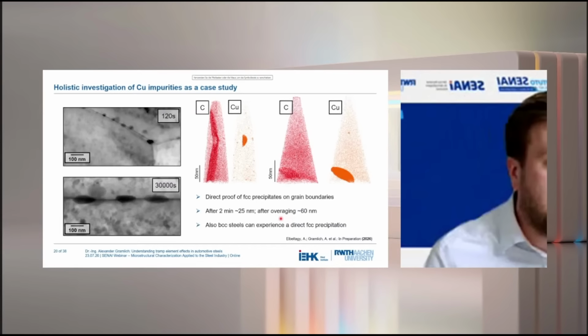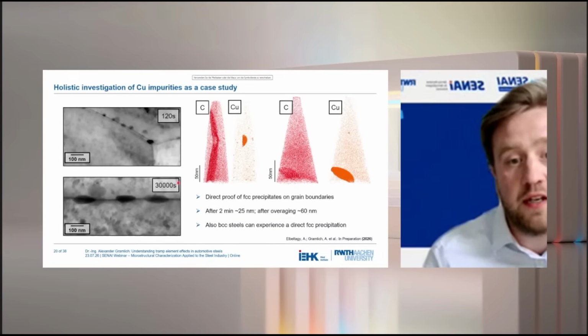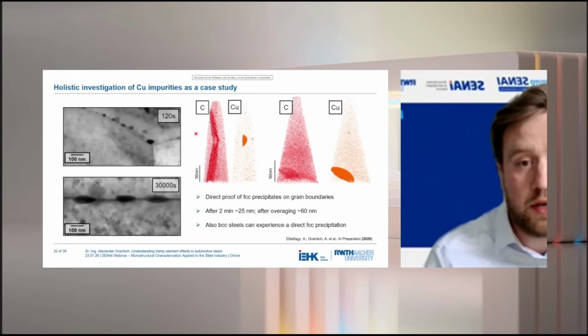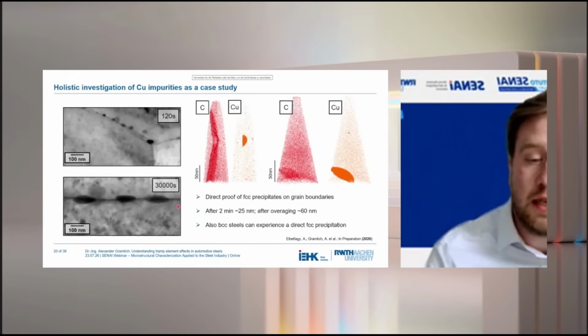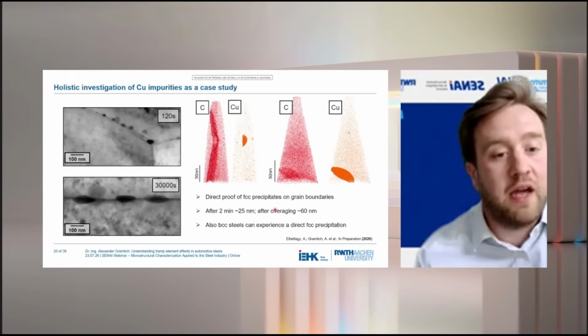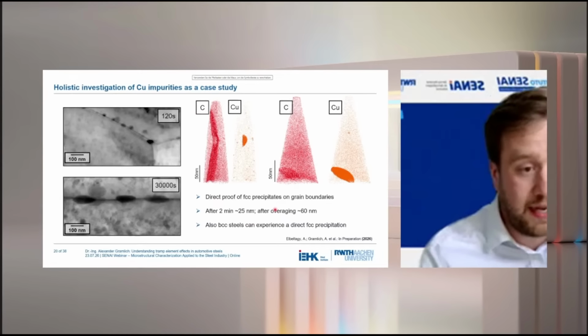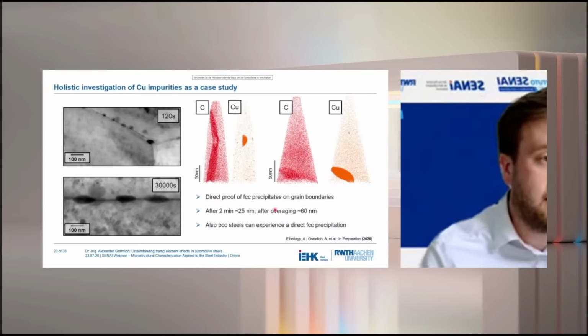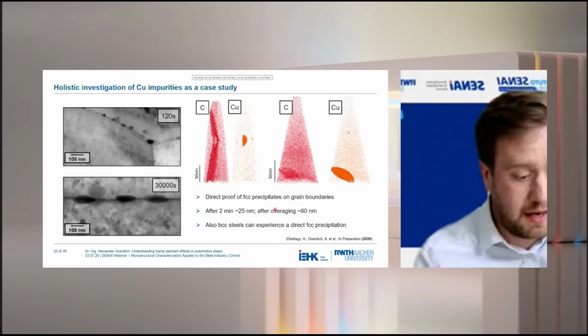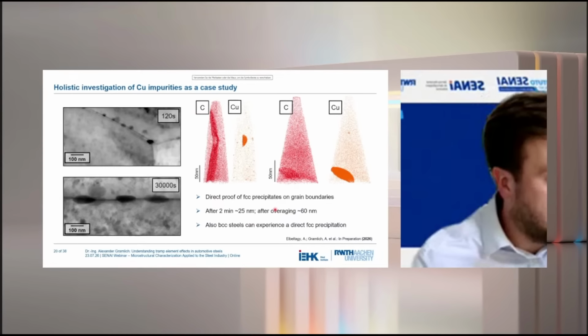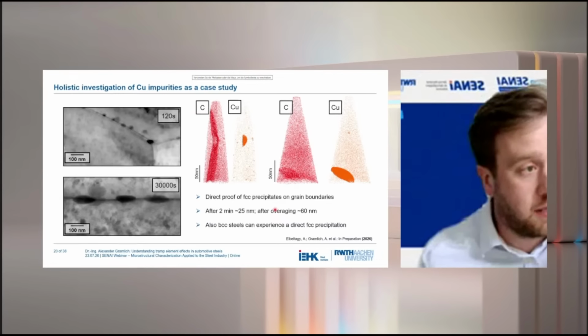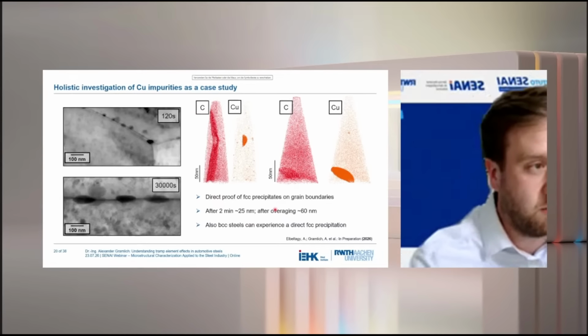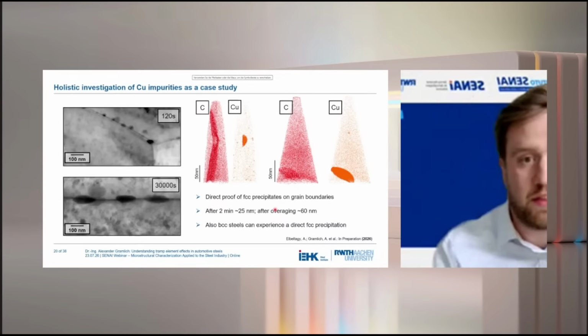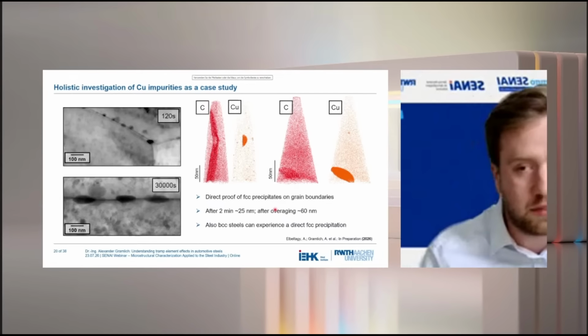Finally, we could also demonstrate this again with atom probe tomography. So we did an investigation after 120 seconds ex situ and after 30000 seconds. And what you can nicely see is that you have a coarsening of the precipitates in dependency of your heat treatment time. Okay, from this we learn there are a lot of precipitates. It's a bit tricky to model them. It's a bit tricky to measure them. However, we can use them for strengthening.